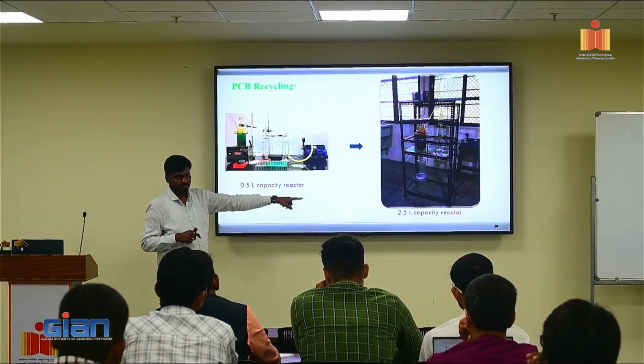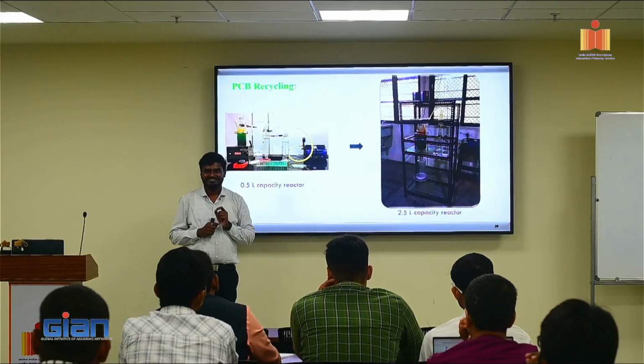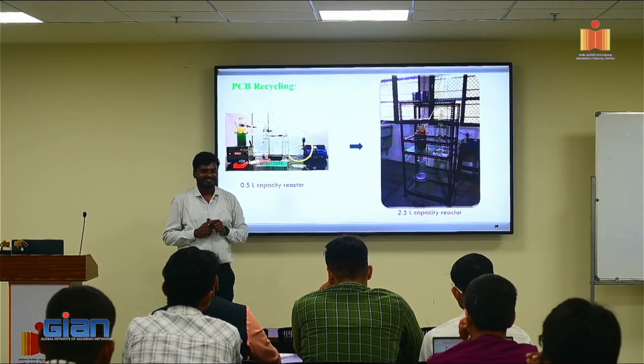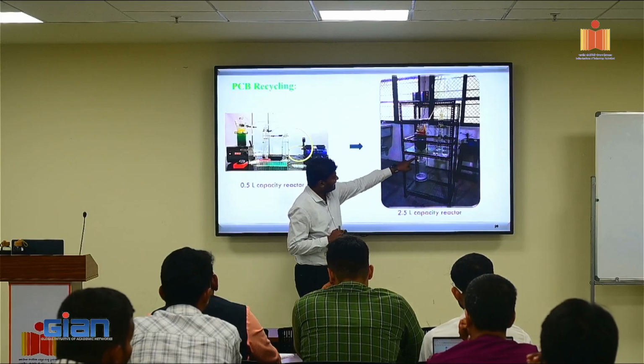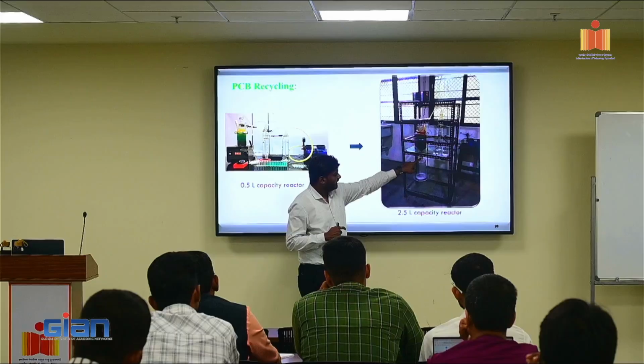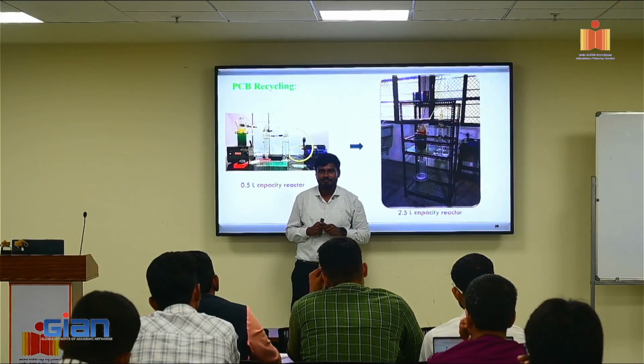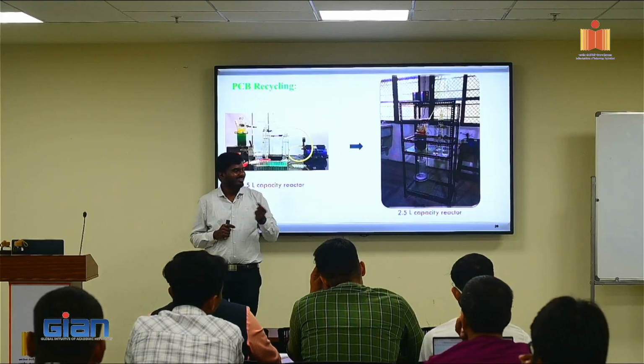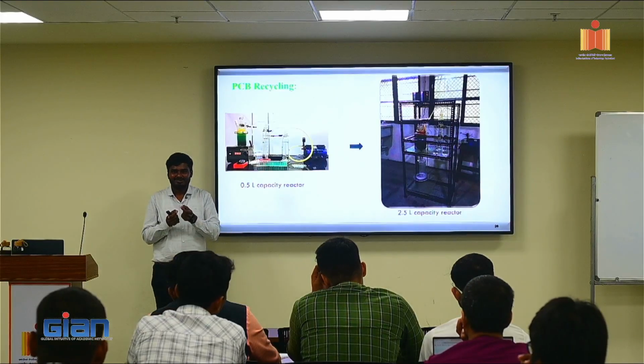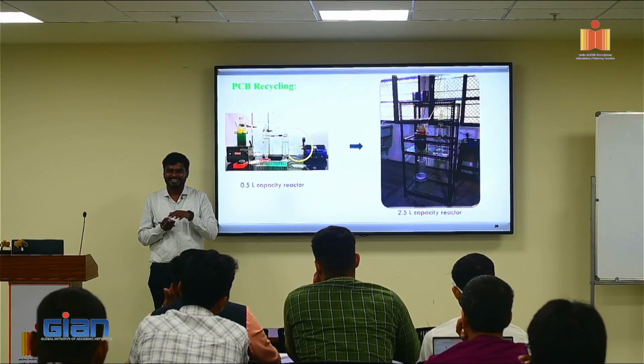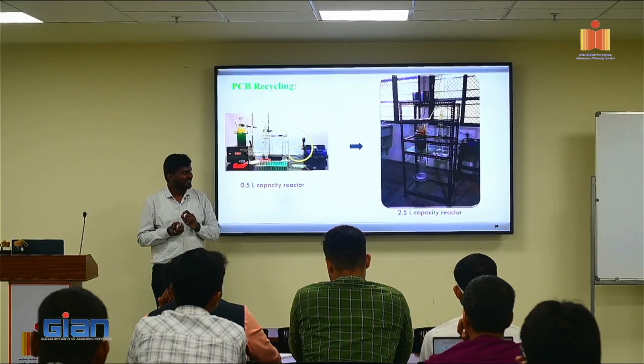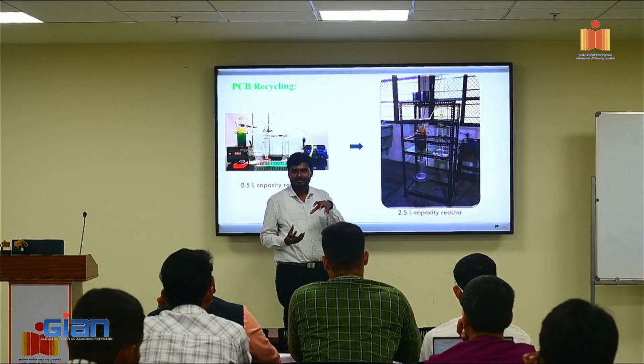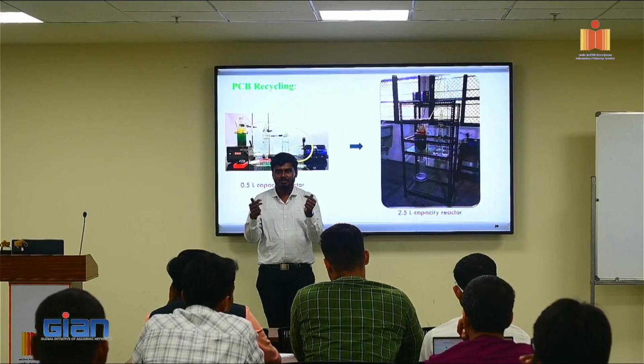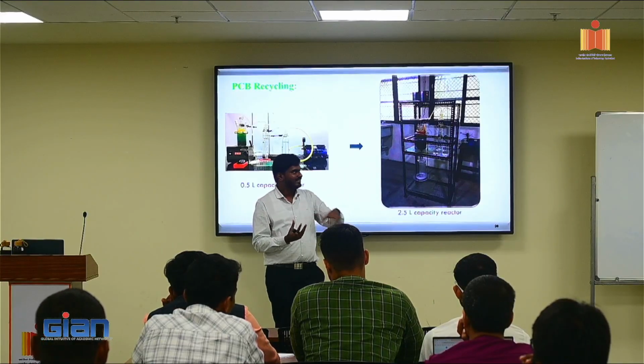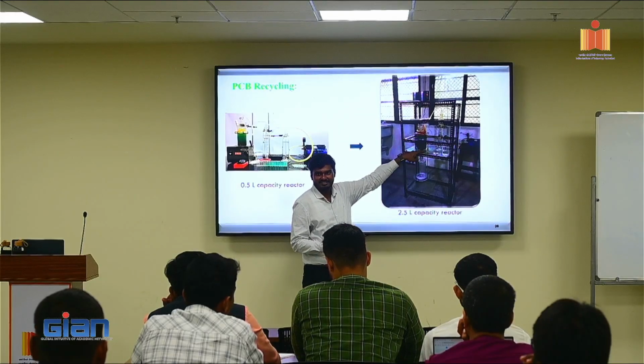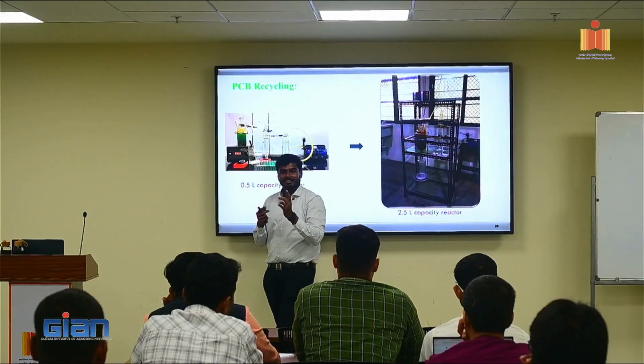When we tried to scale it up to 2.3 liters capacity, we thought we should definitely stop the reaction at 1 hour. So we designed it in such a way that we kept a nozzle at the bottom and wanted to collect the solution. But what actually happens when a nozzle is there, all these electronic components and colloidal solutions will choke the nozzle. If it gets choked, again all metals will start dissolving. To address this, we took a perforated bowl, which means it's like a glass beaker with holes in it. We put PCBs in that and place the beaker as it is and add acid, so that there is a filter between the solid medium and liquid.